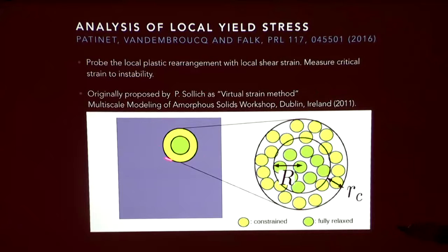The idea was you take some region of the glass and put a frame around it, basically constraining everything outside that frame. So we constrain all the atoms, all the yellow atoms, and then impose some deformation—deforming that region, letting the green atoms on the inside rearrange and accommodate the deformation, doing that slowly until we see some kind of plastic instability.